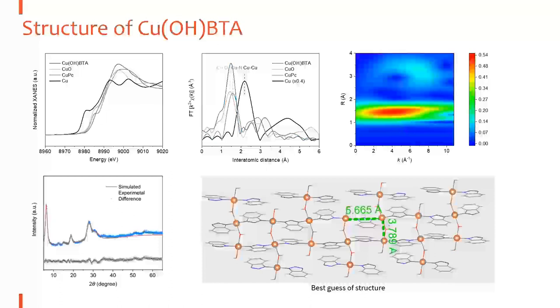So let's look at the structure of this molecule. Of course these dots are copper atoms, and you can see along this line, it's coordinated by BTA molecules, and across this line, two atoms are bridged by OH groups. The distance between two atoms along this direction is around 5.7 angstrom, and the distance in this direction is about 3.8 angstrom. So just have a rough idea of the distance here, because we will be talking about it at a later time.